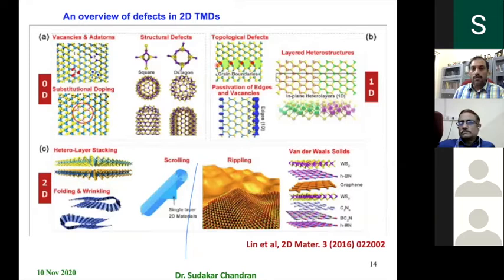The one-dimensional defects are the grain boundaries or the edges. They all form one-dimensional defects, or if you have a heterostructure, the boundary between these two layers forms one-dimensional defects. And if you have a hetero layer stacking of two different materials, then that forms a kind of 2D defect. Also, 2D defects can arise from the folding, wrinkling, the way the sheets get scrolled, and also the sheets are never flat, and there will be a lot of rippling. So these all give rise to the